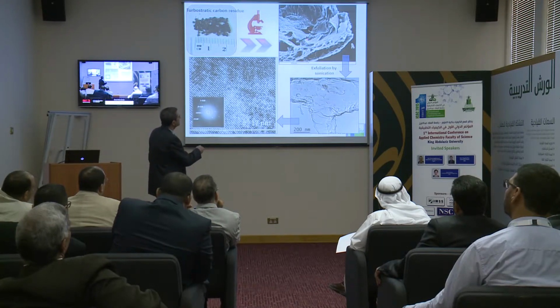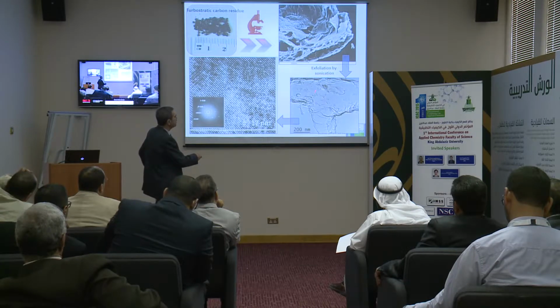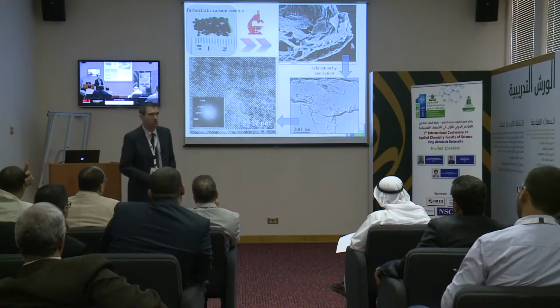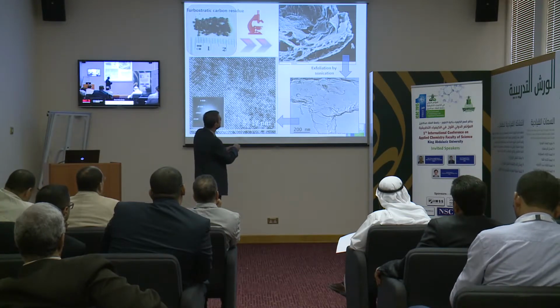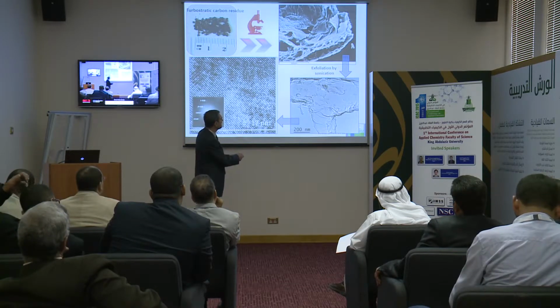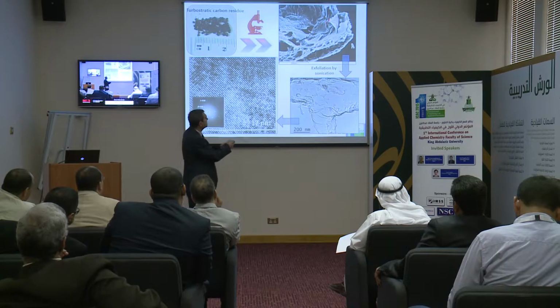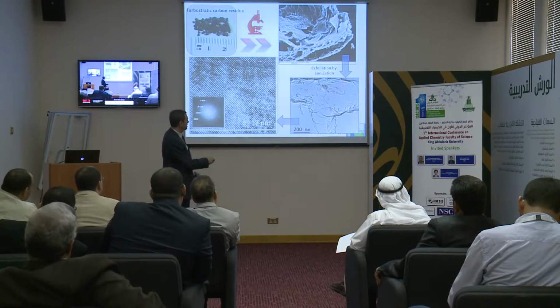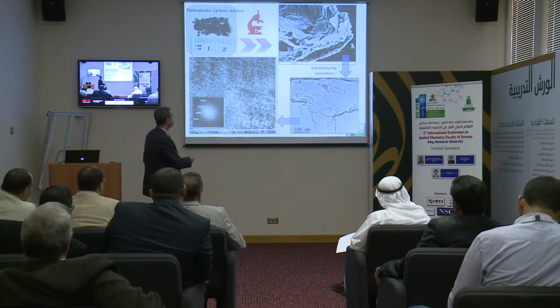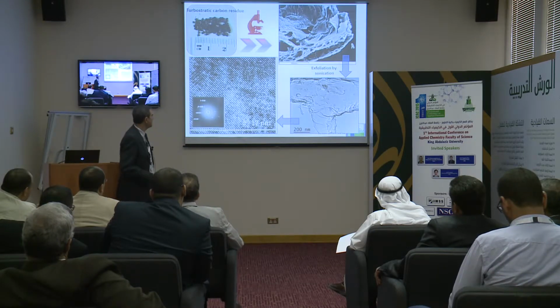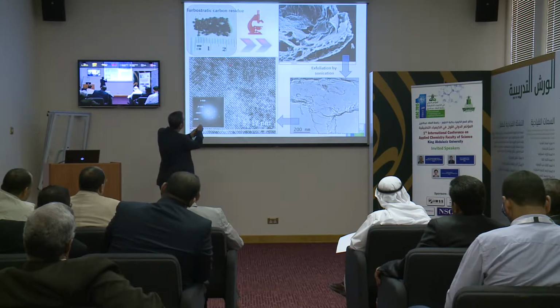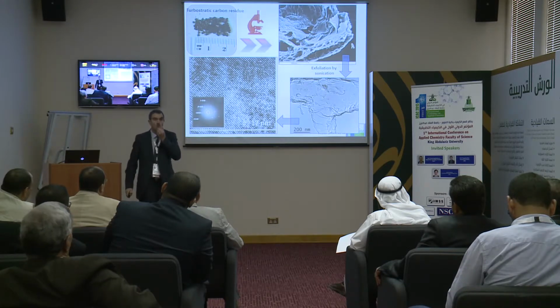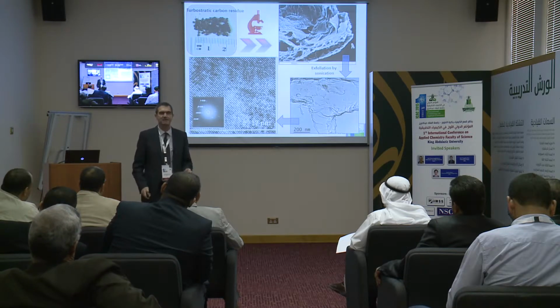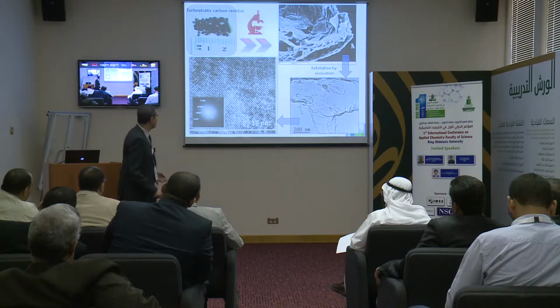So we have this that is made with layers, and then we sonicate and we obtain this, which is the typical appearance of graphene. What you have to notice is the scale, 300 micrometers, and typically graphene is about 1 micrometer. So this layer is really a very long graphene layer. What we are talking about is just a small piece of this expansion. So this is the graphene, and we can even magnify it more and have high resolution electron microscopy. And when you have high resolution, you can really see the order of the atoms in the material. So at different length scales, this is the carbon that we are producing. And the conclusion is that we can prepare graphene in a very easy way, starting from very cheap precursors that have practically no price.